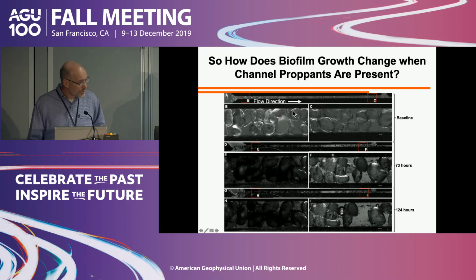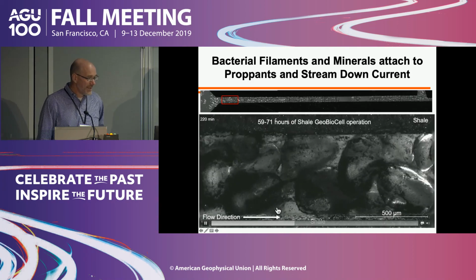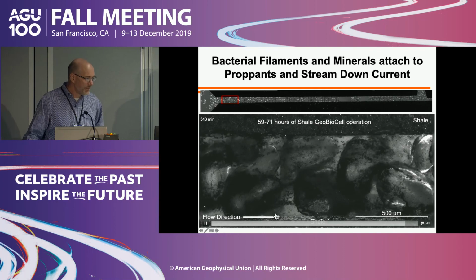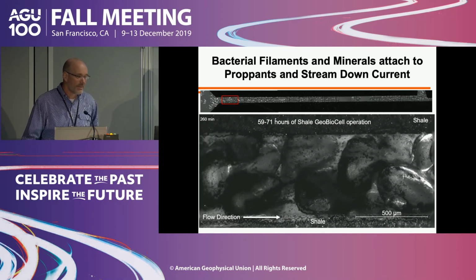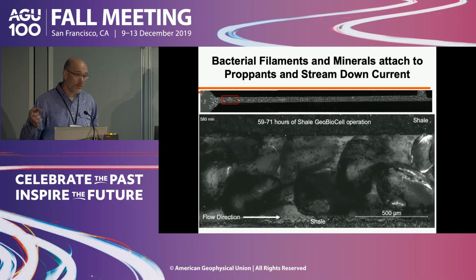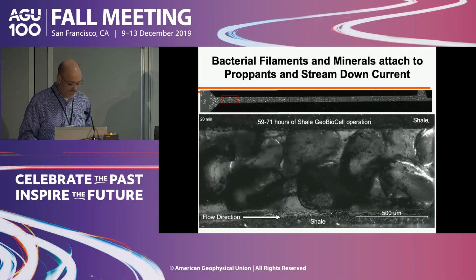The next step was we put proppants in the system. We basically injected these little sand particles into the system. Here they are, you can see them filling the whole system. These are all proppants along that shale fracture. And then this is 0, 73 hours and 124, and this is just upgrading and downgrading. You can see you're getting more and more biofilm forming. It's hard to see exactly where it's at, but there's kind of a slick movie here. At first you think the biofilm's moving, but then you see it's just pulsing. It's like these streamers that are attached to the grains, and they're just moving with the flow of the fluid. So they're attached and staying there.